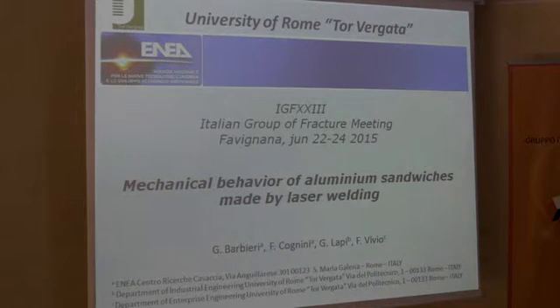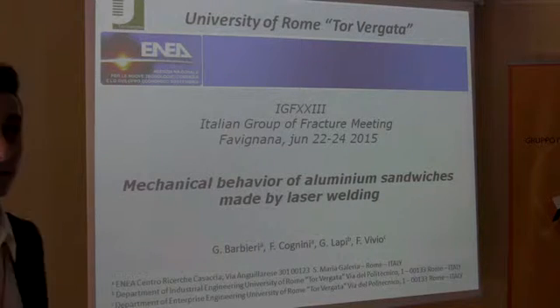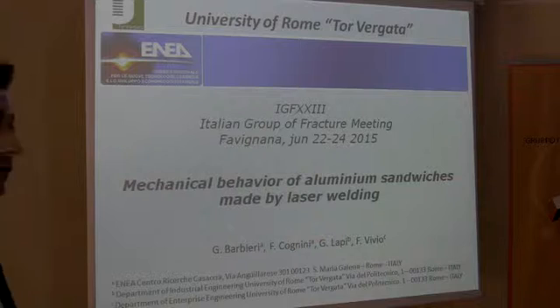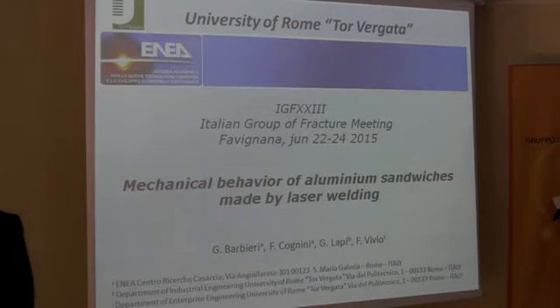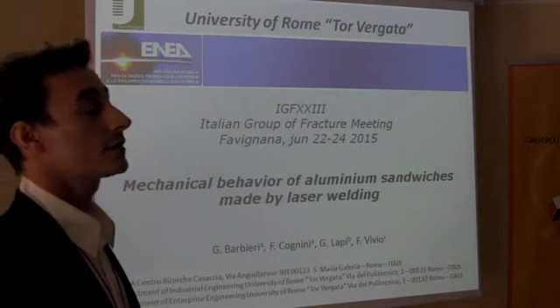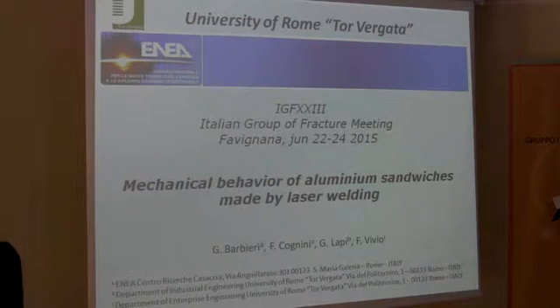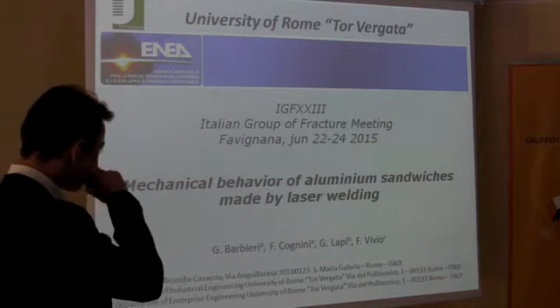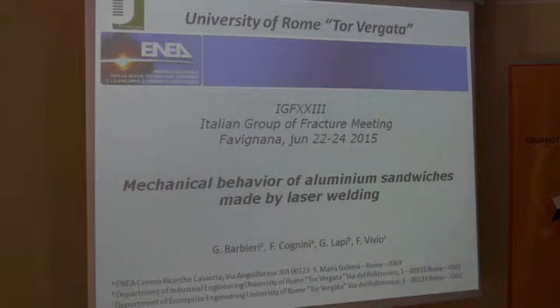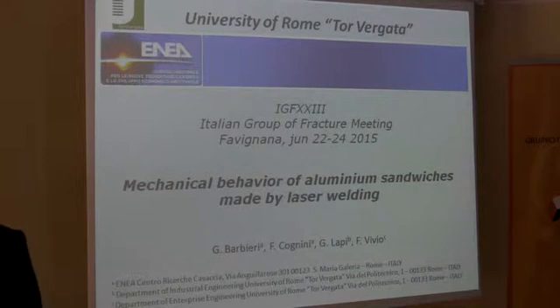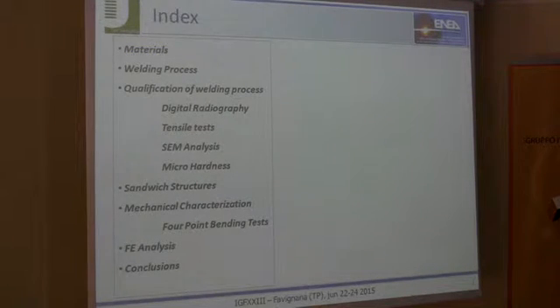Now, aluminum sandwiches are interesting subcomponents for lightweight structures applied in the field of transport. A method to realize this kind of structure consists in welding together extruded profiles to sheets. And in this work, laser technique was applied to join a mock-up of a large aluminum sandwich panel. In this presentation, we'll talk about the qualification of the welding process with digital radiography, tensile tests, SEM analysis, and micro hardness, and then the mechanical characterization of the sandwich structures.